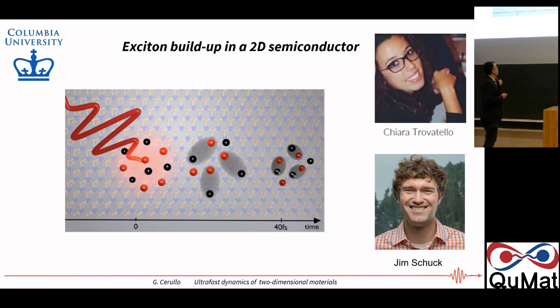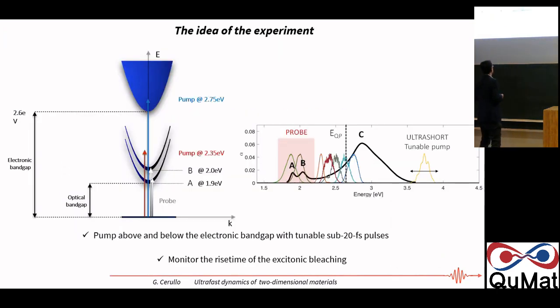So the idea is, if you go above the band gap of this material, you create free charges. What is the time required for these charges to feel the reciprocal attraction and to build up the exciton? Now, the idea is quite simple. Here you see the A and B excitons. Here you have the electronic band gap, where you have essentially free charges above this. And now we will use very short pulses, on the order of 20 femtoseconds, and we will tune the energy of these pulses over a very broad range, from the visible all the way to the ultraviolet. So we will give a lot of excess energy, and we will monitor the rise time of the so-called bleaching signal of the excitons.